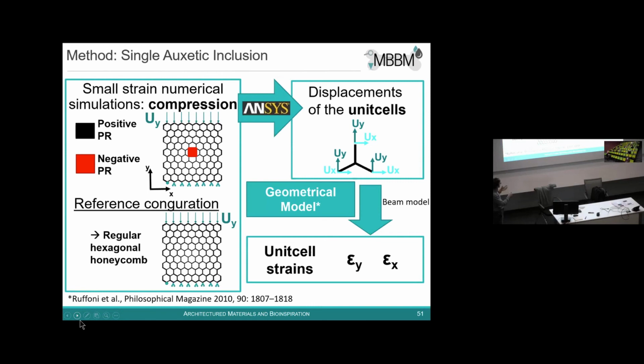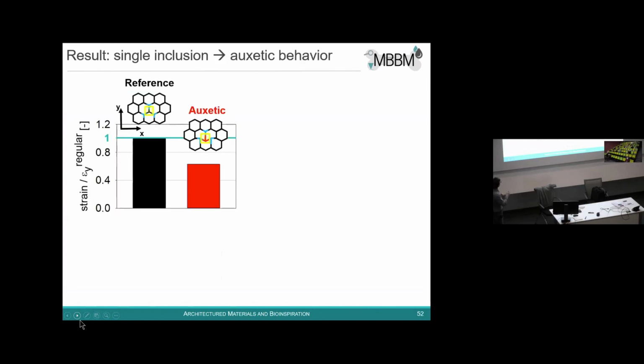So with the simulations, we could get the deformation in each point. We consider these triangular unit cells, which are the basic unit cell that you can repeat in space to build up your hexagonal lattice. And by knowing the displacement in each of the vertices of this unit cell, we could calculate the overall strain of the unit cell when it is inside the regular lattice. If it's inside the regular lattice, the strain is everywhere the same. This is an isotropic structure. And the question is, what is happening when we have an auxetic inclusion here? And what we saw is the following.